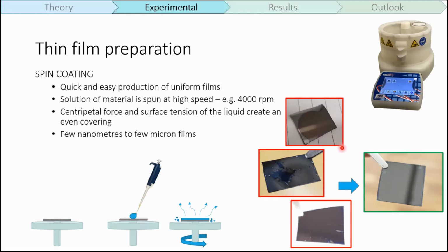At the beginning we had a lot of challenges producing such uniform films as you see now in the green bracket. For example, one issue was that the film wasn't dispersing or covering all the substrate, or it formed such uneven absorption that we get spots, or even comet streaks, such as seen in the third picture.